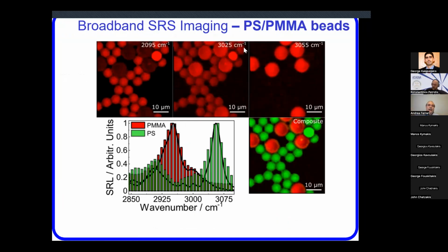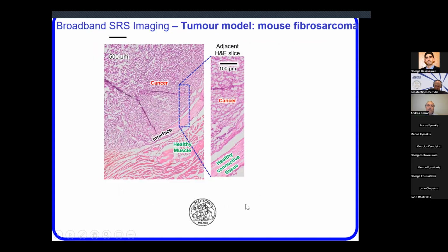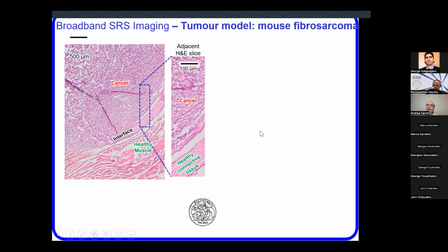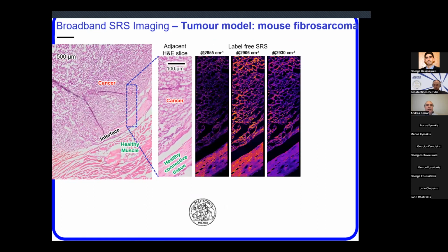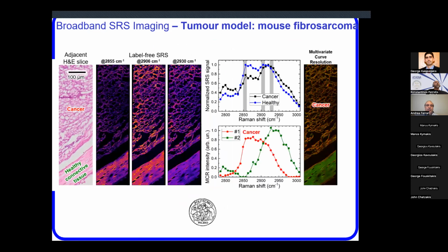The first test is done on polymer beads, PMMA beads, and you can distinguish the two compositions very easily. But actually, the real test is to take a real biopsy with cancer interface and so on, and then you take the coherent system, and you can get a label-free image, no dye. Of course, because it's a Raman map, you can plot at different frequencies, and this is an ginormous amount of information for the medical doctor when they are trying to identify if you have cancer or not, and if there is a transition.